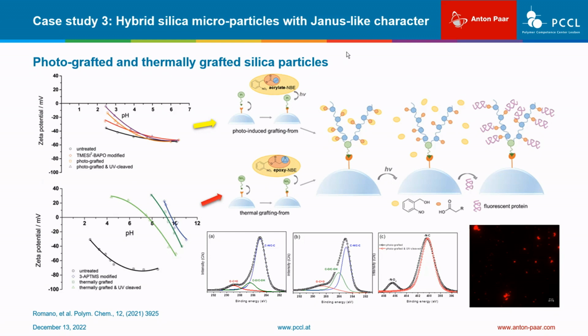Here you can see the synthesis procedures for the fabrication of the photoresponsive hybrid particles. We carried out two surface modification strategies. In the first approach, the immobilization of a Norrish type 1 photoinitiator with functional trialkoxysilane moieties on the silica surface was followed by visible light-induced grafting of a monofunctional acrylate with NBA groups. Photoresponsive polymer brushes are obtained with free carboxyl groups upon subsequent UV exposure.